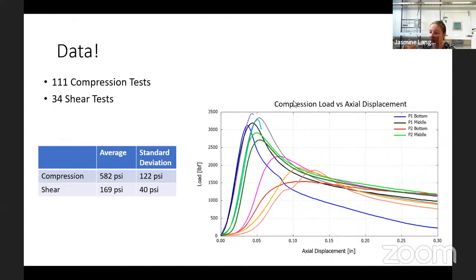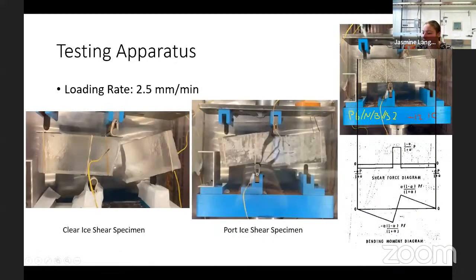Question: can you show which parts of the testing apparatus are moving during the test? Yes, the bottom was fixed and the top was pushing down. The top plate was actually on a swivel, so we could line it up correctly. And there's a counterweight up here, this little orange thing, because the plate would otherwise be lopsided when we were testing. We would lower it down so it touched, and make sure it's perfectly aligned. Then we added a preload of about 10 pounds, and then we would test it.